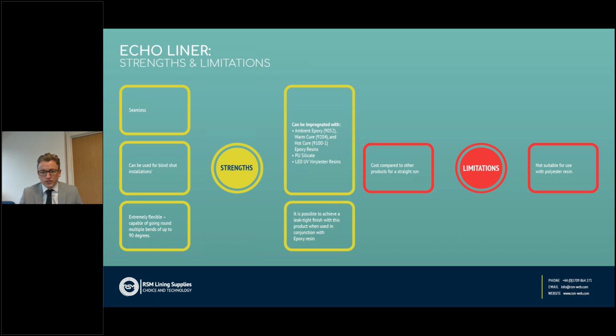Now, the limitation is that if you were to use this on a straight run, similar to the SUPERFLEX, it is a more expensive product, so it does need to be used on more flexible options of 90-degree bends, etc., rather than using it in straight runs. Another limitation is that it's not suitable for use with polyester resin. If you impregnate it with polyester resin, the styrene from the polyester will attack the coating and then start to delaminate the liner.